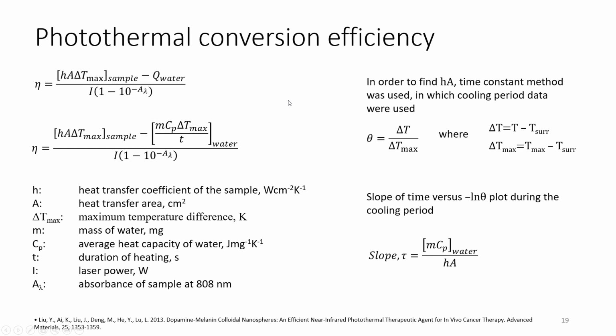To calculate photothermal conversion efficiency, we use this equation. The only thing we don't know in this equation is heat transfer coefficient. To find heat transfer coefficient, we use time constant method, which uses the cooling period data with dimensionless temperature. So the slope of time versus minus natural logarithm of theta plot during the cooling period gives the time constant, and from time constant we can calculate the heat transfer coefficient.